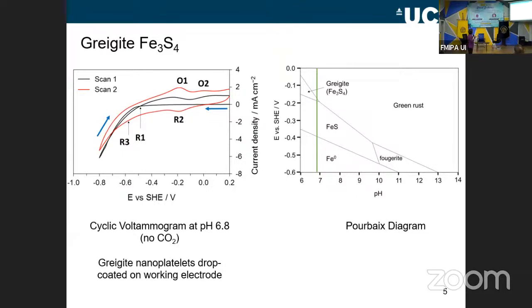I'm doing this reaction at pH 6.8, and there's no CO2 in the solution at present. So really, going from 0.2 down to minus 0.8 is the equivalent on this diagram of starting at a positive potential and moving to a more negative potential down this green line. The green line is drawn at pH 6.8, and I'm starting from the top and moving down. So what I would expect to happen is that my greigite hopefully will be stable because I put the layer on it. Then I will get a reduction of the greigite, my Fe3S4, to FeS, which is just iron 2. And then I should get another reduction to iron 0. So that's what I'm expecting to happen.